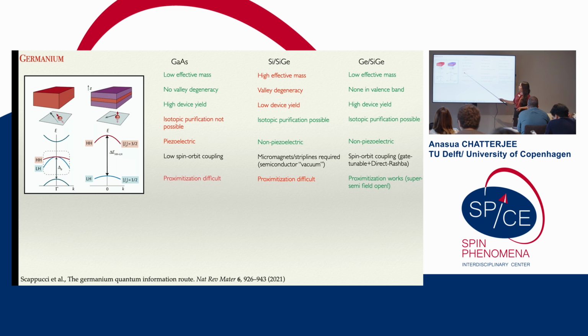So one thing is that by working with heterostructures, as Giordano does, you kind of lift away the heavy holes and you have a separation of the light hole and heavy hole. Then you have a low effective mass in germanium, which is something that in silicon gives us a lot of headache, because due to the high effective mass, you have to make very small confinement, and you're at the kind of edge of your lithography, and so you kind of end up with low device yield. You also have this valley degeneracy, which we saw previously that you can get around, but we like that germanium doesn't have these valleys to lift your spin blockade, for instance.